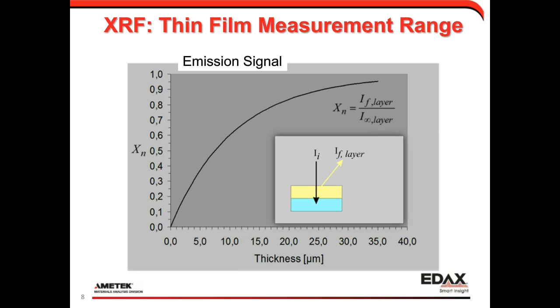So you have a lot better sensitivity to measuring thin coatings versus the same sort of signal that would apply over, let's say, 50 microns, where now your range of signal applies over a much thicker type of sample. When you get above somewhere in the range of 80 to 90%, then small changes in signal near the asymptote result in large changes in thickness measurement, and it becomes more impractical in this region to make measurements. So there'll be some sort of a cutoff at the max limitation for these types of measurements, and that's what we'll show in the examples. All right, so let's jump back into the presentation here.